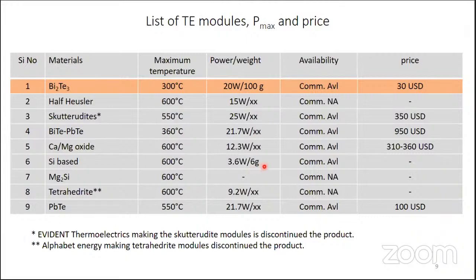Why is this so exorbitantly costly? Because of the engineering they adopt to make this material thermally stable. It is the engineering they adopted to make this module out of this material, to protect it from oxidation, to protect it from sublimation, to protect it from any degradation of the hot side contact. All these things make these modules, usable at 500, 400, 600 degrees, very costly.